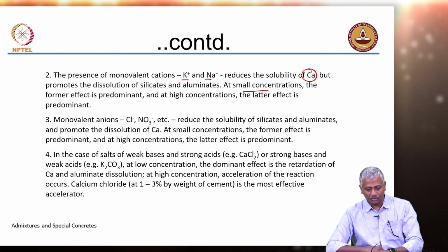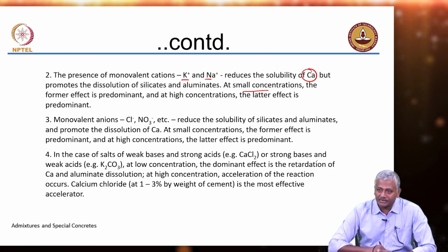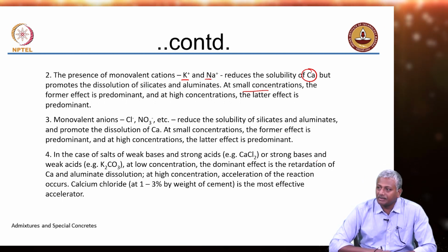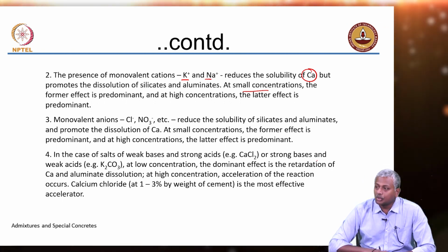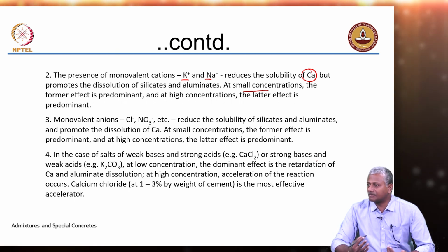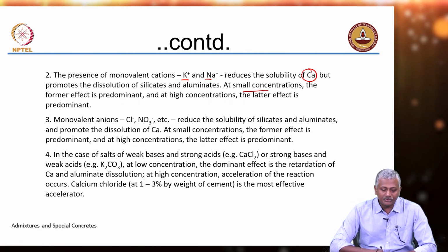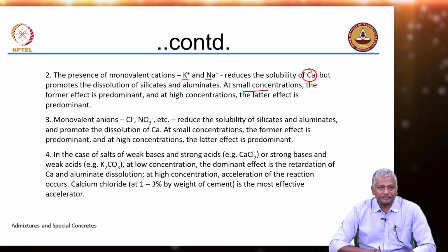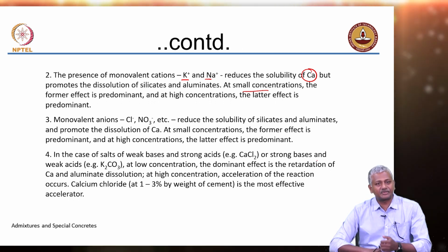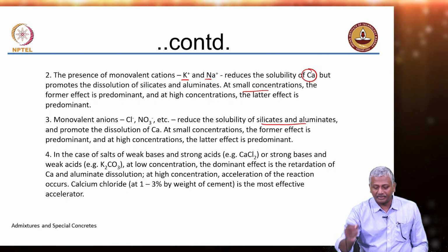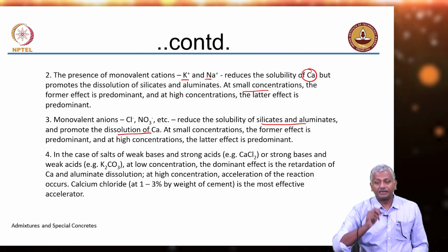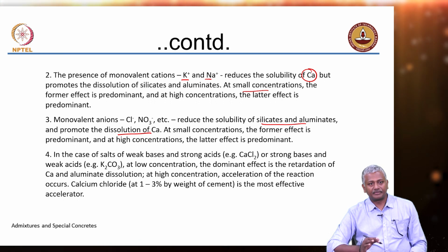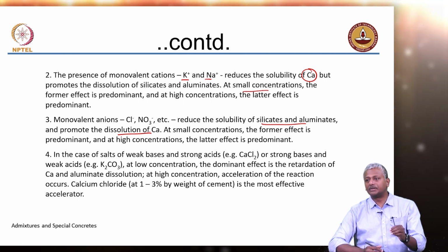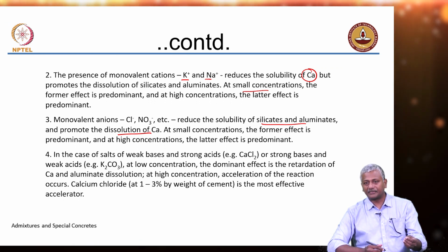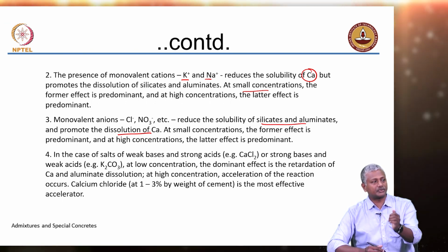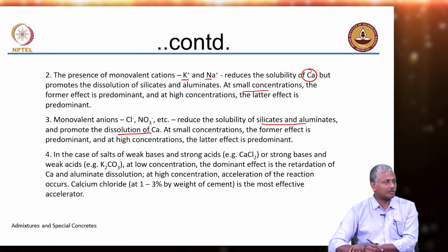At small concentration there is retardation, at high concentration there is acceleration. Same goes for monovalent anions like chlorides and nitrates. They reduce the solubility of silicates and aluminates, negatively charged species, but promote the solubility of calcium. It turns out that at small dosages this is dominant, at high dosages that is dominant. So, that means that if you use a chloride based accelerator, you need to add high enough dosage so that the dissolution of calcium becomes the dominant phenomenon.